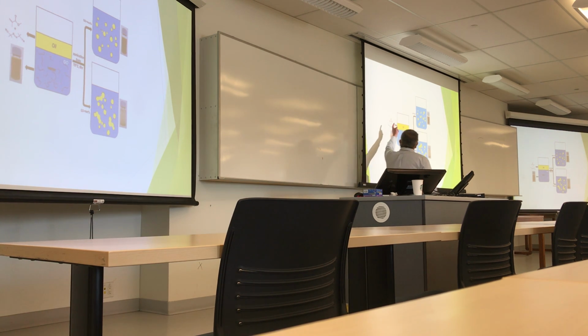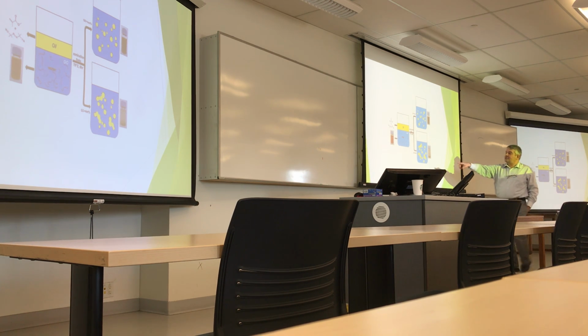So here we have again MMA, and we had water and GO, and we used sonication. What happened was that we had different concentrations of GO and we got different products. When you had quite a bit of GO, more than 4%, GO wrapped all of the PMMA particles, or droplets. And then when it was less than 4%, we started collecting all the PMMA that it had, and it started creating all sorts of structures.